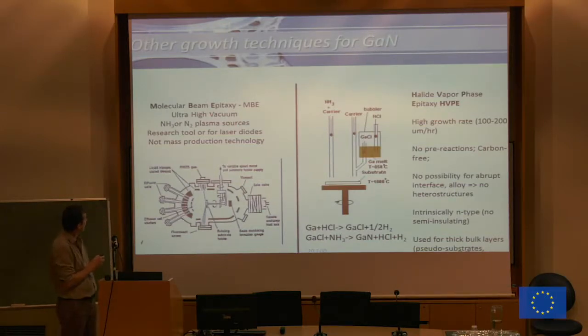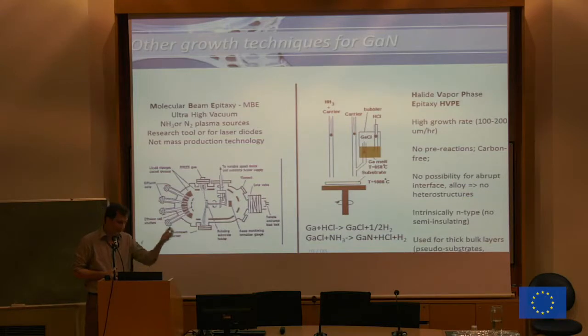There are other techniques that can obtain the same. One example is molecular beam epitaxy, where your source materials are really the atomic sources. So it's a block of gallium or a block of aluminium that you use to do the deposition. Another possibility is HVPE, where you in fact carry gallium from a melt into your reactor with a chlorine carrier gas.